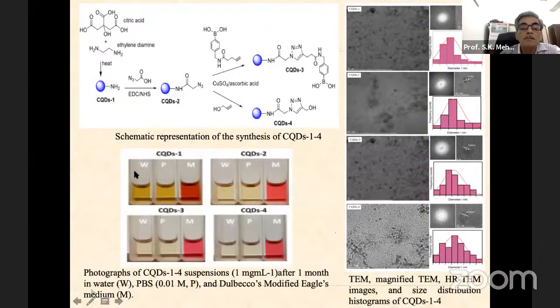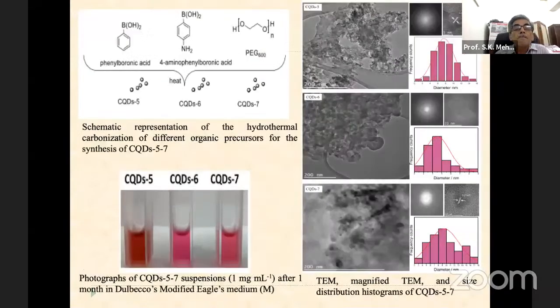So this you can see, this is in water, this is in PBS, and then this was the prepared medium, and they saw that there is a color change. So a colorimetric change was there, and using different quantum dots, the color was slightly different. They measured the particle size also, and you can see how the particle size varies and the distribution is different. So this is quantum dot 5, quantum dot 6, 7, and so on. Again, you can see there is a colorimetric change, and using TEM you can see the size.